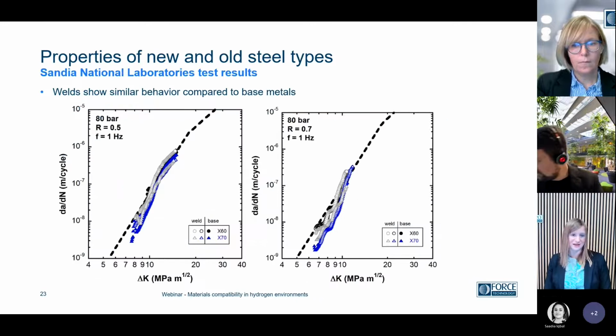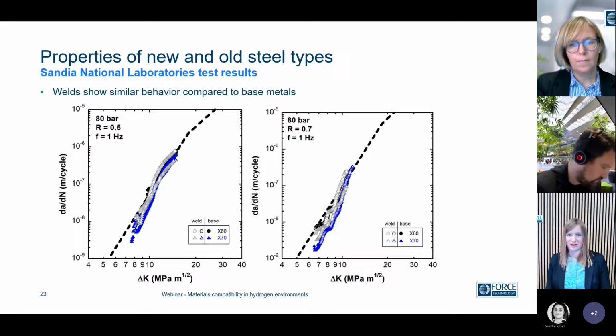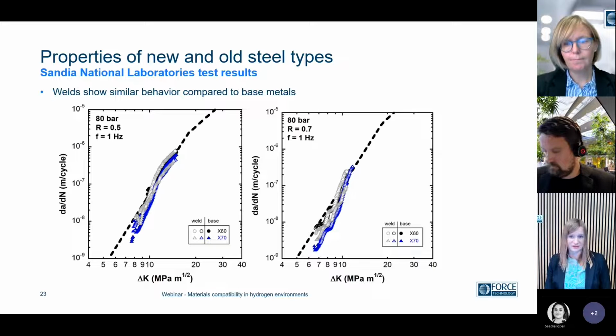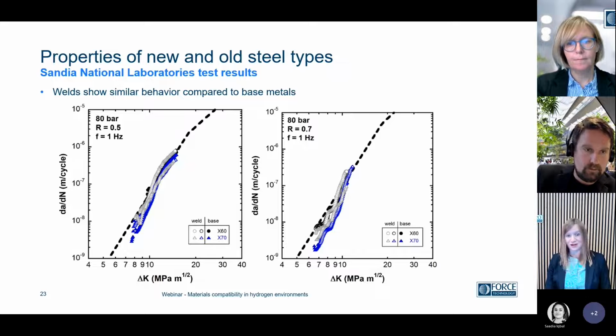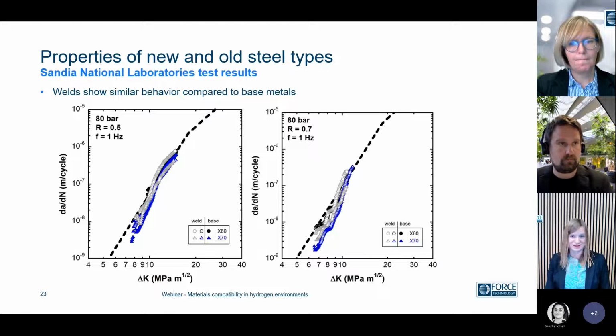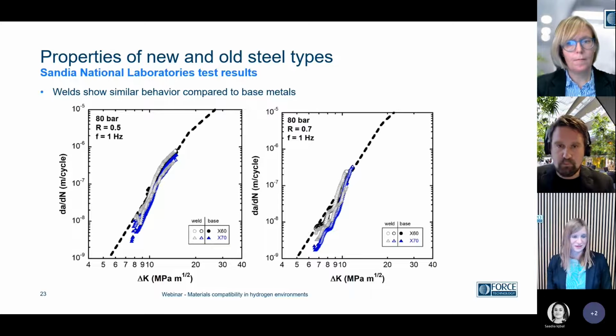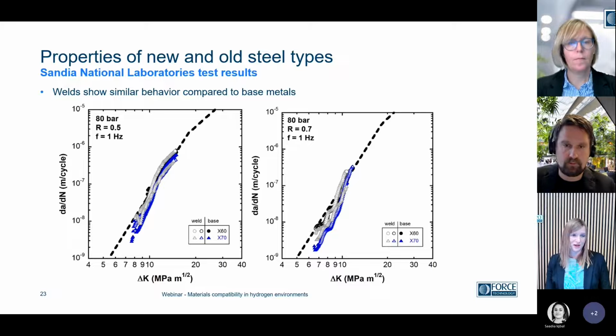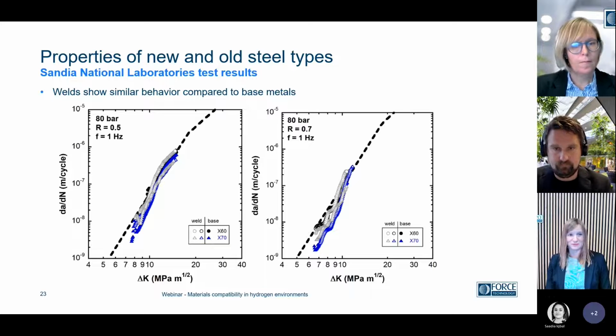What about the welds? That is the most critical area of the pipeline because you have inhomogeneous properties compared to the long sections. The Sandia National Laboratories have tested welds versus base metals. This is fatigue crack growth rate curves for X70 and X60 steels at 80 bars. And 80 bars is a very relevant pressure for the European hydrogen backbone infrastructure. That's a normal pressure for onshore gas infrastructure. And the black curve you see is the ASME B31.12 master curve. And we see the results are below this master curve, and that it's quite a similar behavior for weld and base metals. This, of course, needs to be studied in more detail, but it's a promising sign.